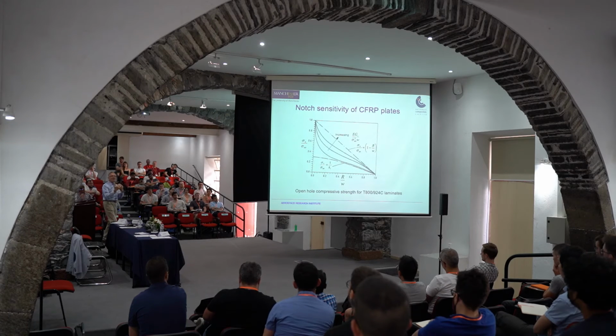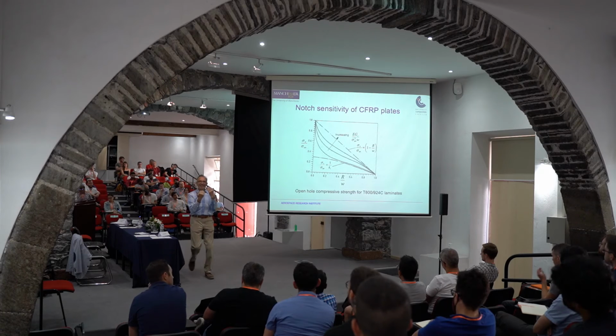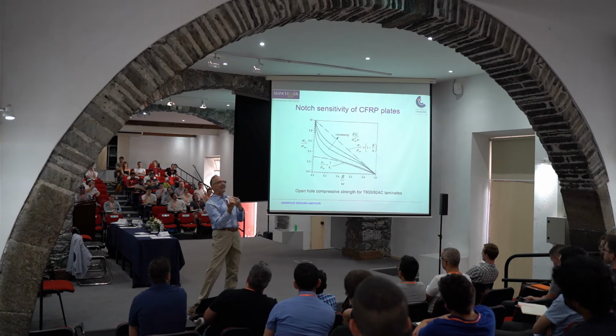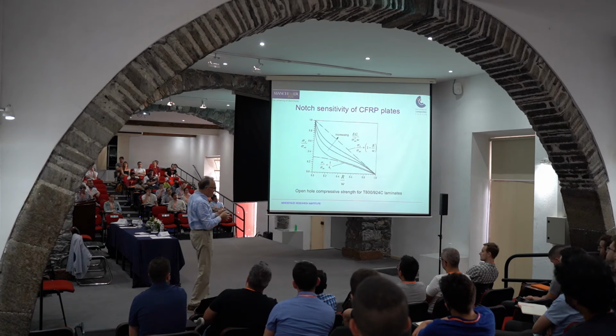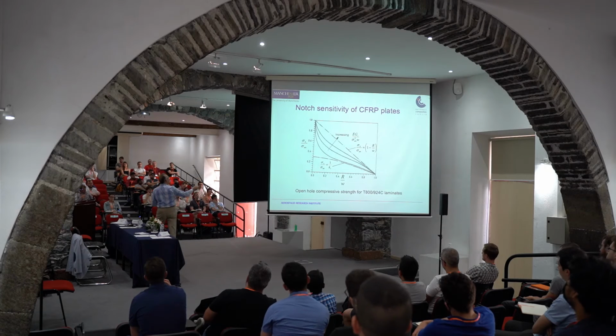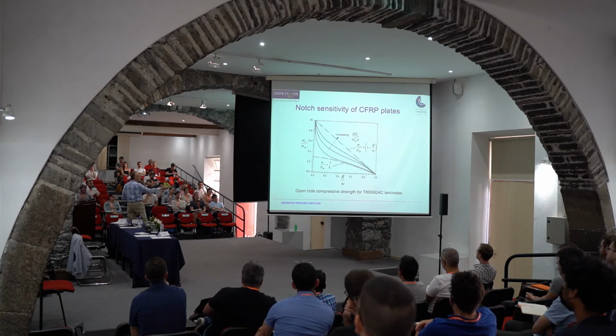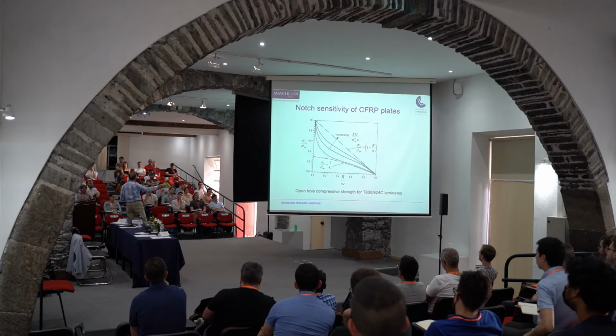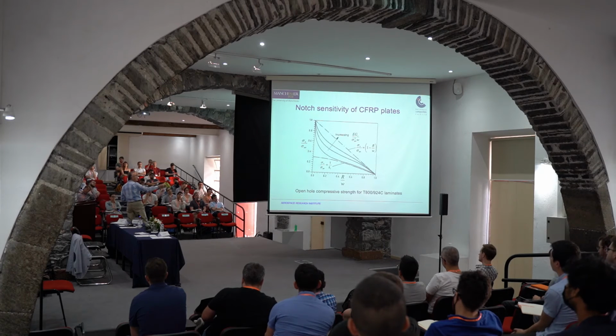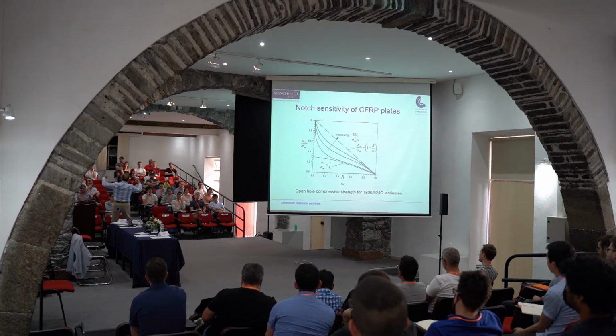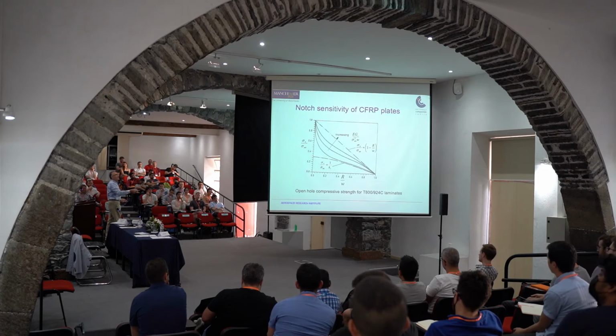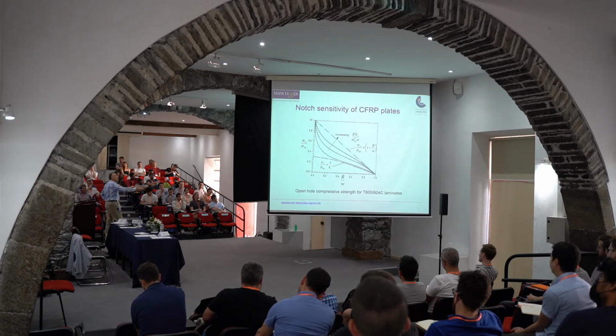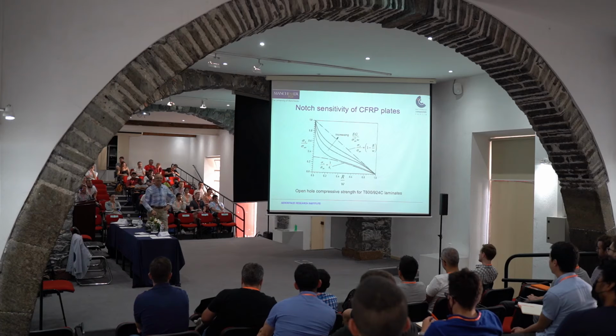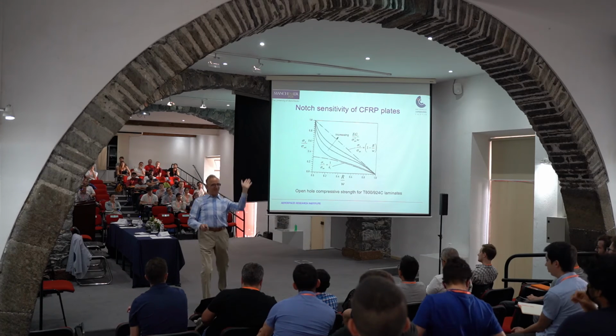And now the composite falls somewhere between those two ideal cases, the ideally notch sensitive and the ideally notch insensitive. And the task of the designer is how to set up layups so that they approach the upper curve, which is the notch insensitive curve. And of course, these are critical parameters: the overall elastic modulus of your laminate in the loading direction, the GC, the critical strain energy release rate associated with the fiber microbuckle, the unnotched strength, and the geometry. So if I put lots of plus minus 45s, I can create a more notch insensitive case.